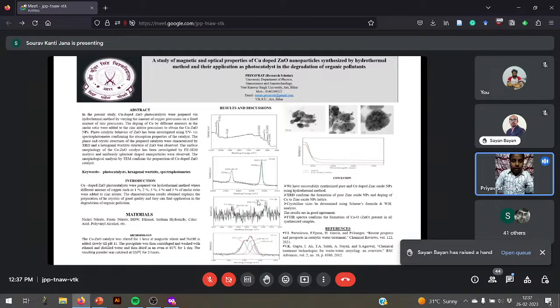The FESEM analysis was used to check the surface morphology of the Cu-ZnO catalyst. The figure shows the lower and higher magnification morphology of Cu-ZnO, where uniformly distributed spherical shaped nanoparticles were obtained through this experiment. The EDS analysis of Cu-ZnO shows the existence of Cu, Zn, and O elements in the present samples.